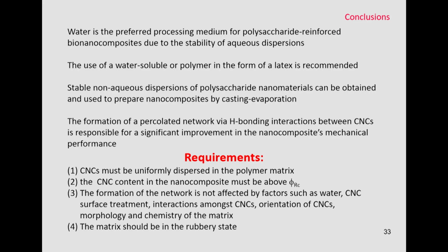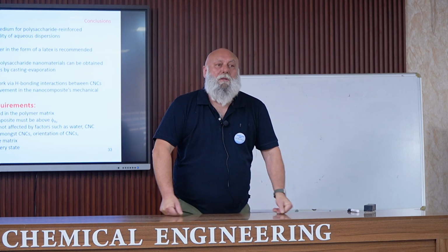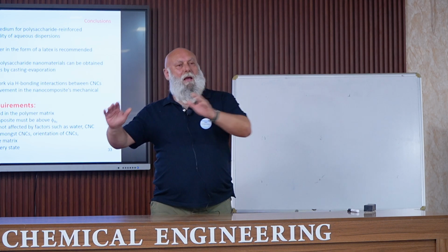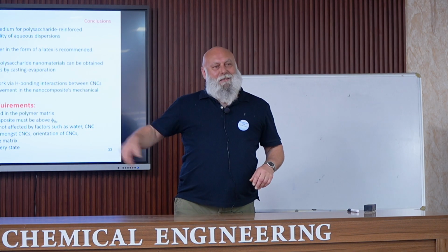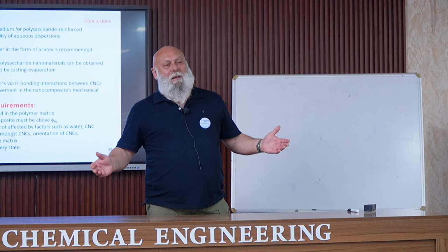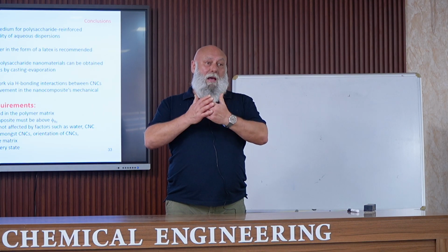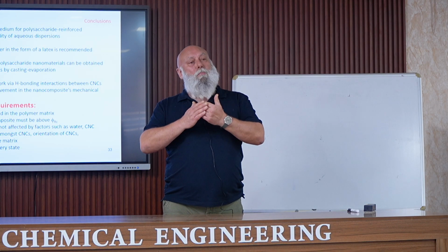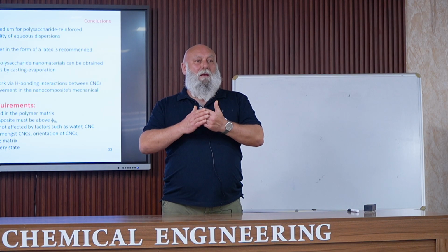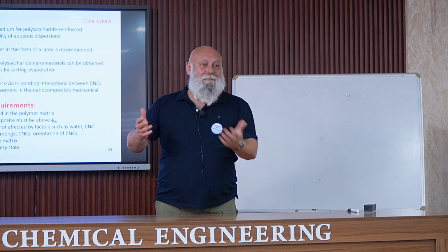Ionic liquids? No, not myself, but most probably some have tried. We have tried some quaternary salts, I will show you later. And yes, it worked, but it's always the same story. If you want to avoid aggregation, for this you need to block the OH groups from the surface. And if you block the OH groups from the surface, you cannot form the continuous network.